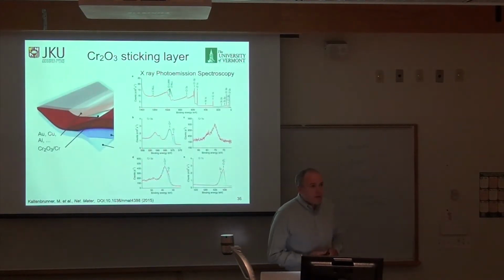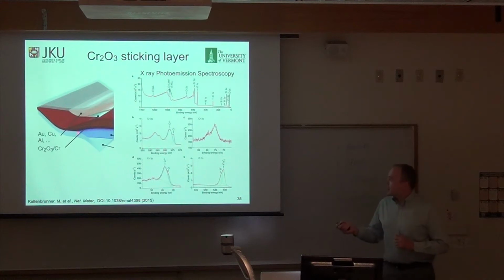So what we did was we deposited a very thin layer of chromium under a slight oxygen partial pressure to get a chromium oxide sticking layer right at the surface. Chromium oxide is very stable against these halogens. You put down this chromium oxide layer, and I demonstrate this here - this is the XPS, X-ray photoemission spectroscopy data that shows that we do have this oxidation state of the chromium at the interface.